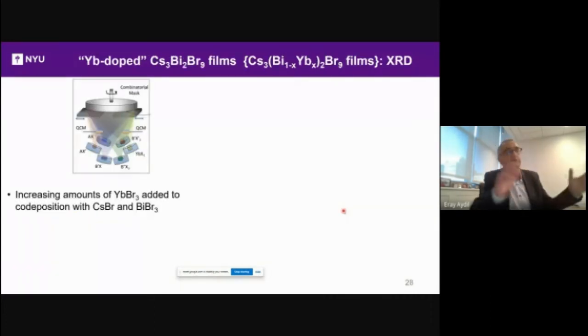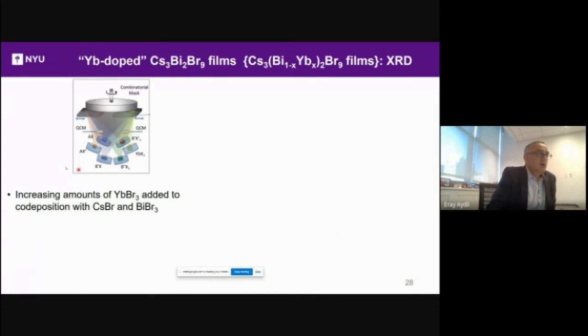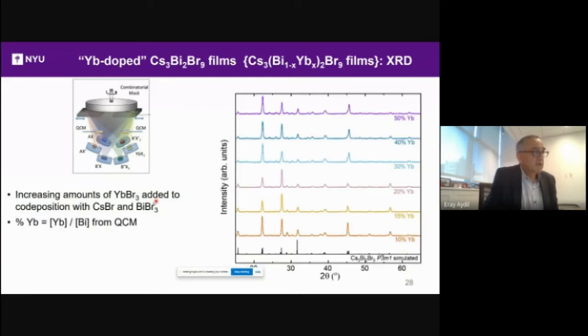Okay, so now, getting back to quantum cutting, let's do ytterbium doping and see if there is any conversion into the near infrared. So we increase the amounts of ytterbium bromide added to the co-deposition of cesium bromide and bismuth bromide. So we turn on another one of the sources. And I'm going to report percent ytterbium as the ratio of ytterbium to bismuth.